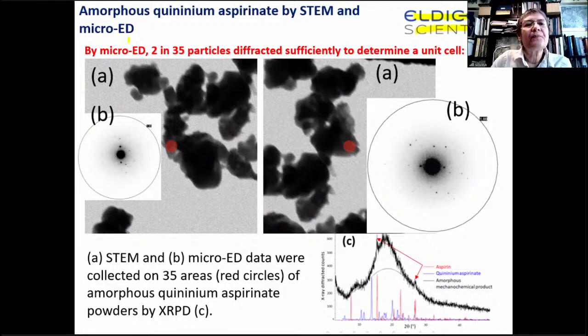And we can see scanning transmission electron microscopy micrographs, with these red zones where the electron beam was also used for diffraction. They tested 35 particles, and 2 of those actually diffracted the electron beam. We can see here these diffracted beams as those dark spots around the central beam. So that means that not all of the particles were really amorphous. Most of them were, but not all. So this is the powder diffraction data.